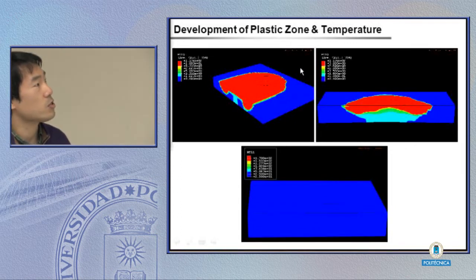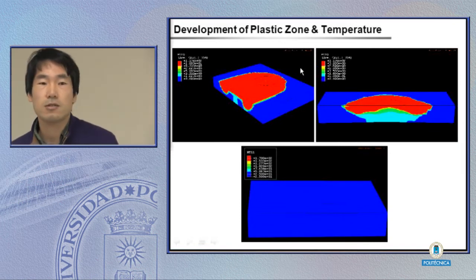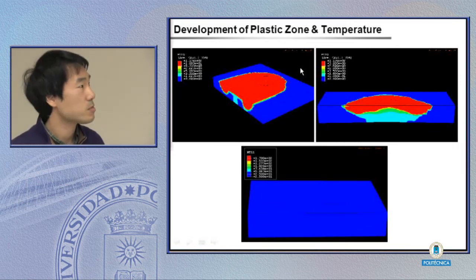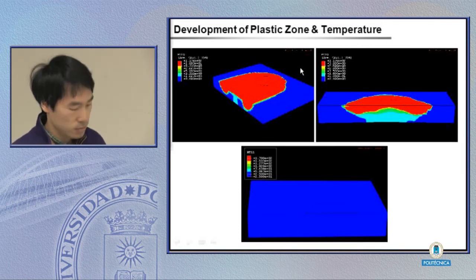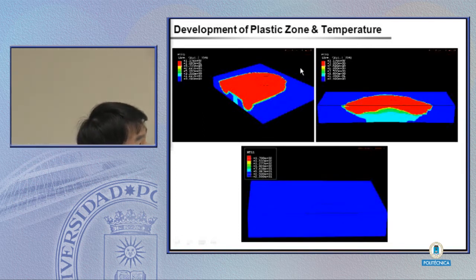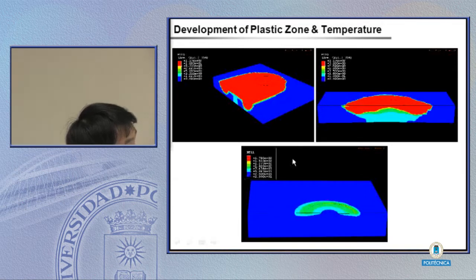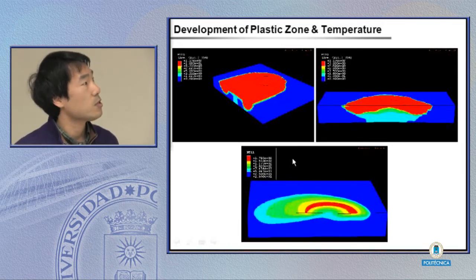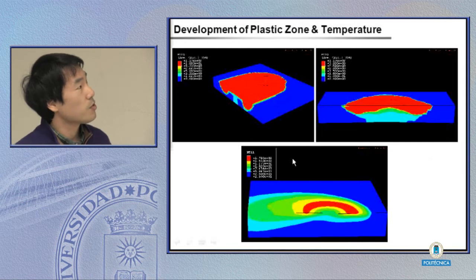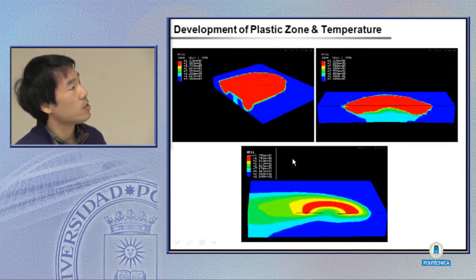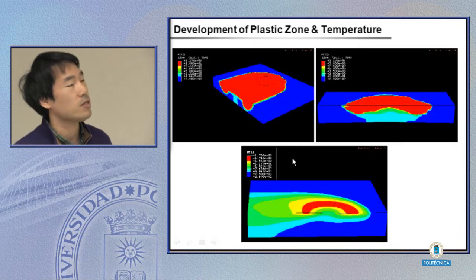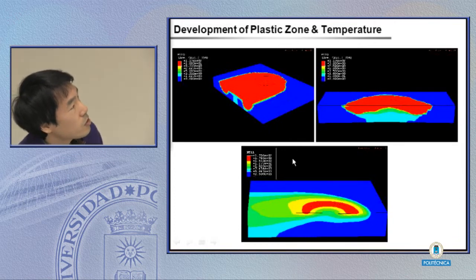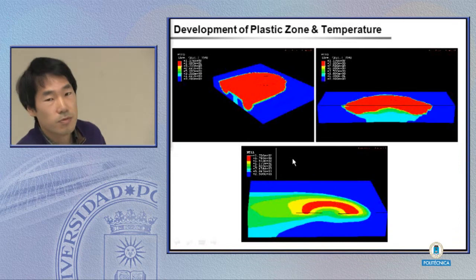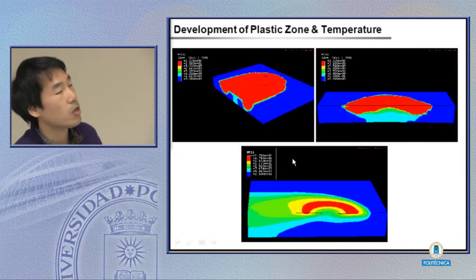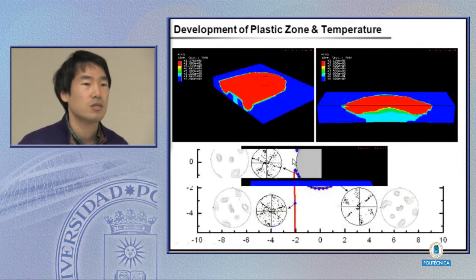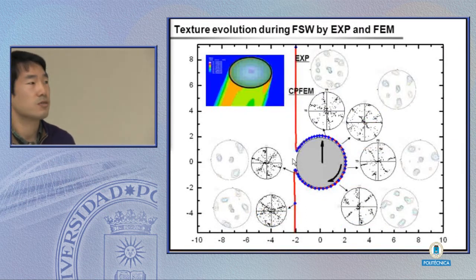The first feature is the plastic deformed joint cases. As you can see, with the stirring of this joint, it develops the plastic deformed joint. You may not see the exact value at the highest of the plastic strain case. It's over 100%, so it's too much severe deformation.